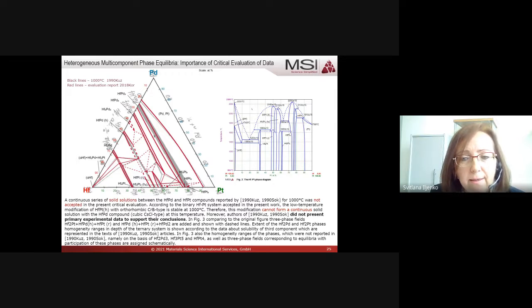So the red lines, these are already redrawn by our authors by breaking this continuous solid solution. And if you make out of one phase now two, then of course there must appear other 2 and 3 phase equilibria, and they are shown here in dashed lines because they are not reliably established, but this is just the assumption of our authors. Since the continuous solid solution is not possible, there must be a 2-phase field, and this of course will cause existence of some other 3-phase fields here.